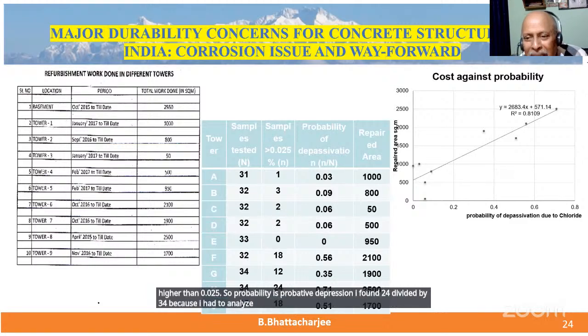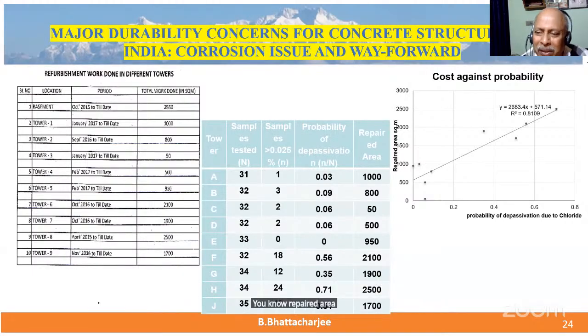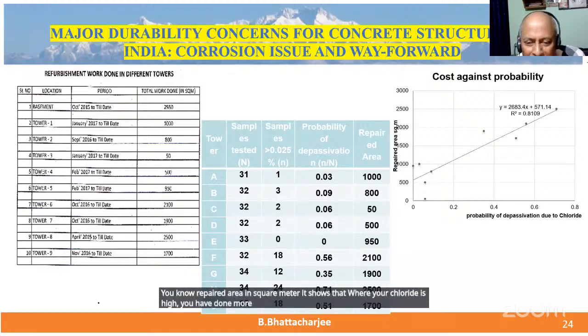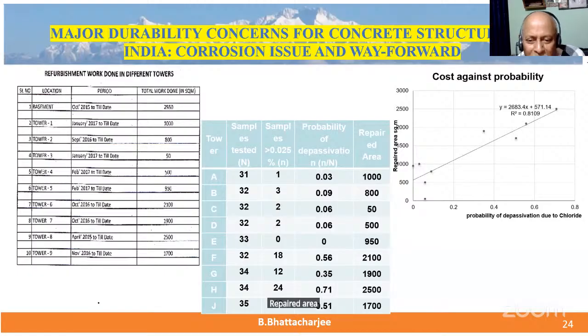analyze. And then I plotted this probability of depassivation versus repaired area in square meter. And it shows that where your chloride is high, you have done more repair. For example, repaired area for 0.56 probability is 2,100, 0.35, 1,900, and so on and so forth, and you can fit a curve to this. So this is one case.